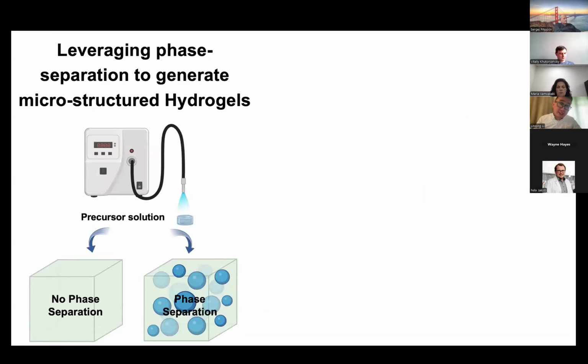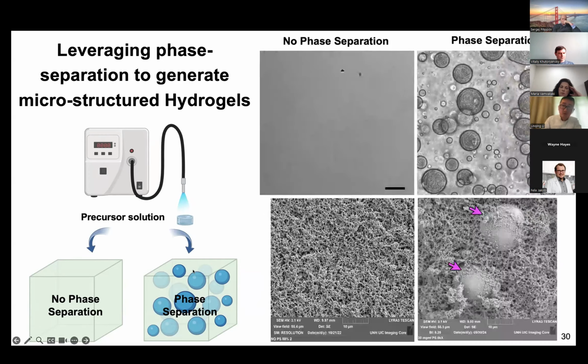utilizing these methacrylate groups that we modified to the backbone. So the idea is that you can have the same chemical composition. One is no phase separation, the other one is phase separated. So essentially we have the same chemical composition, but by triggering the phase separation, you can create two physically completely different structured hydrogels. So shown here on the top is your phase contrast.